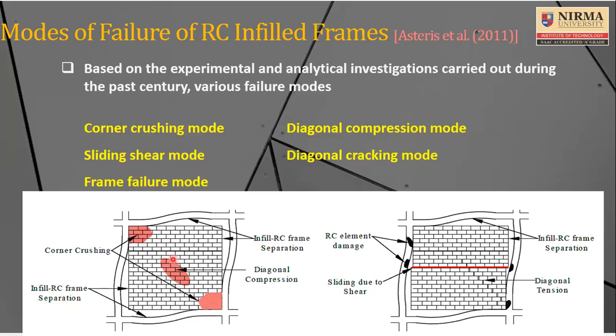You can realize from these failures that some of the predominant or typical failures observed under lateral loading are corner crushing. As you apply the lateral load, one diagonal will try to elongate and the other diagonal will try to get compressed, and because it is undergoing compression, the effective length of this infill will decrease, and because of this reduction in effective length, it undergoes corner crushing. In between, it will be subjected to diagonal compression on one side, but on the other side it will be subjected to tension, and because of that diagonal tension, the infill will start cracking in terms of a diagonal crack, like a stepped joint. It undergoes a stepwise failure because of the tension.